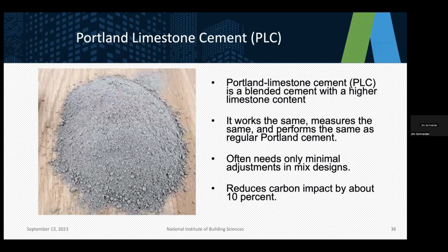So Portland limestone cement is a blended cement with a higher limestone content. So it works the same as traditional Portland cement, measures the same, and performs the same. There often can be minimal adjustments in mix designs, and it can reduce the carbon impact by about 10%. But of course, because it is something that is a little bit different and can have some variation, engineers can sometimes be a little bit wary of just going 1-to-1 and thinking it's going to be just right. So there's still some kind of feeling it out with PLC. But it is becoming more prevalent. We're seeing it quite a bit more in specifications, and more producers are starting to use it.